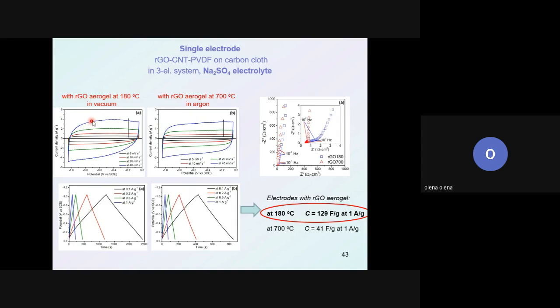And also we have some pseudocapacitance here. It's visible in comparison with this one. And this is impedance, both of them show capacitive behavior. Even reduced graphene oxide obtained at 700 shows slightly higher capacitive properties. When we calculate the data, the capacitance for the first type of electrodes with RGO at 180 shows a 3 times higher value.